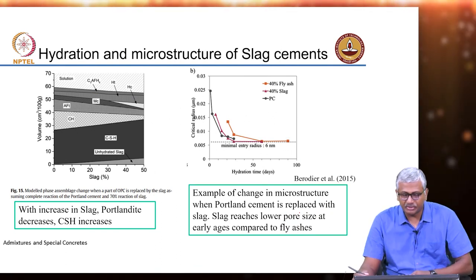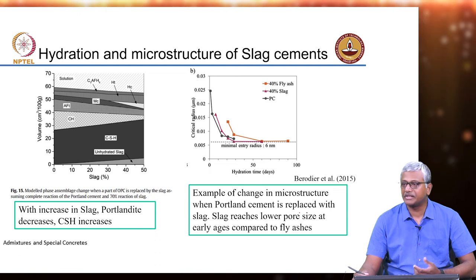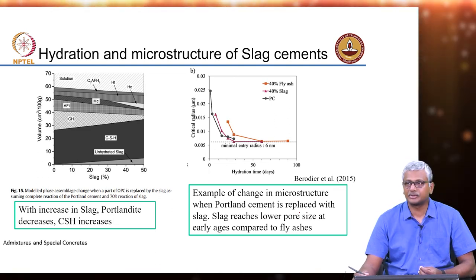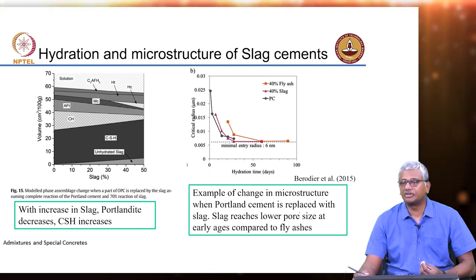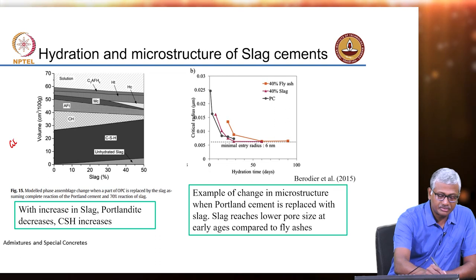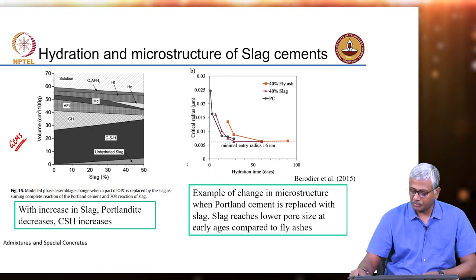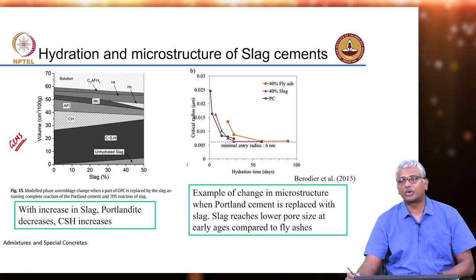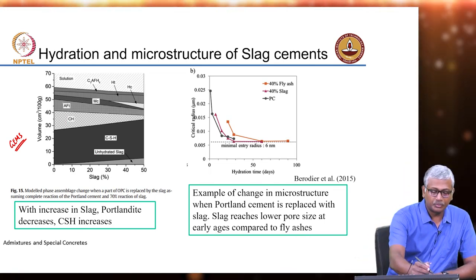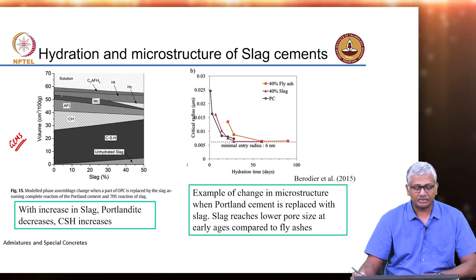Some aspects of hydration are presented here. There is some reactive silica, so portlandite consumption will be there, but please remember that slag has enough calcium on its own — the decrease in calcium hydroxide content with the presence of slag is not going to be as substantial as with other active alumino silicates, such as calcined clay. This is actually a model for hydration called the GEMS model — Gibbs free energy minimization model — based on how the thermodynamics of the system evolve and what products could form from a given mixture of reactants. So here they are talking about slag, portlandite, ettringite, and whatever remains in the first phases of cement hydration.